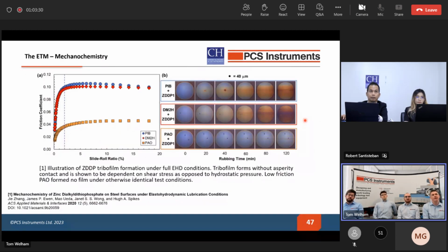From a mechanochemistry side, this comes from a paper published in 2020, and just very quickly, it shows how previously it was thought that the development of ZDDP films required metal-to-metal contact. But actually, using the ETM in this paper, it was shown that rather than hydrostatic pressure being responsible for tribofilm growth, it's actually shear stress dependent. So we can have a full film, but if the shear stress is high enough, we can still develop ZDDP films.